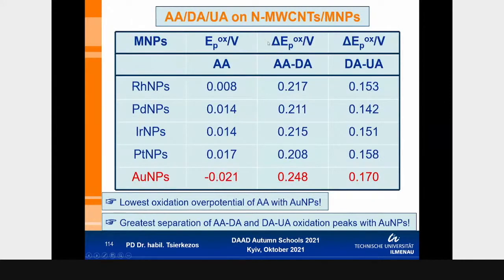So I summarize all the results in this table. You can see from these results that by using gold nanoparticles and modifying the carbon nanotubes, you can reach a negative overpotential of ascorbic acid, which leads to a greater peak separation between ascorbic acid and dopamine, and of course to separated oxidation peaks between the three biomolecules, which is important because this helps for measuring all three compounds in a single measurement.